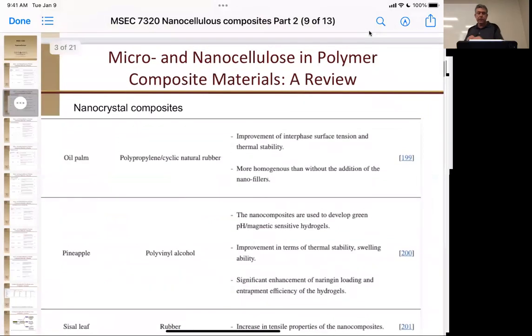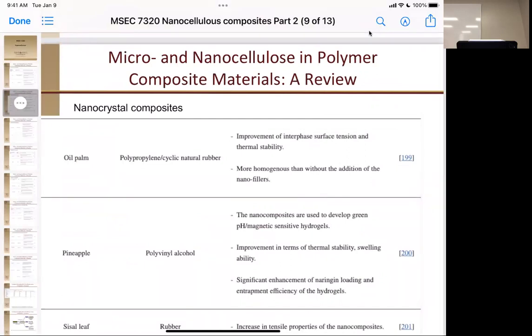Okay, so then if we got the nanocrystals out of oil palm, the actual palm fronds from oil palm, and mix it with polypropylene and rubber here, we saw an improvement of interphase surface tension and thermal stability. What is interphase surface tension? So polypropylene is a very non-polar polymer, right? And the natural rubber is probably going to be a lot more hydrophilic. So what we're seeing here is that the polypropylene doesn't want to interpenetrate with it and mix perfectly. So they make phase domains. But if you have your material at those phase domains, there's some parts of the rubber that can bond to it, and the polypropylene is probably just crystallizing on the surface there, giving it a better interface. And that better interface means you change the thermal stability of it.